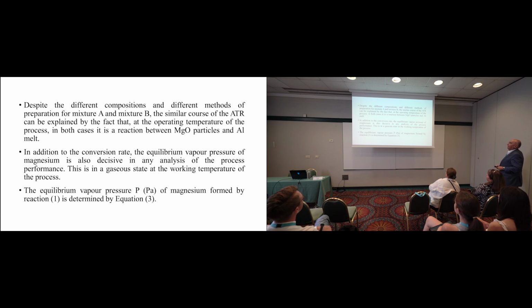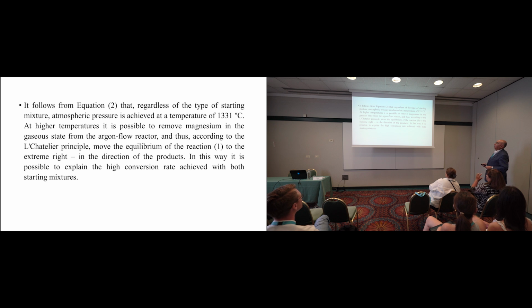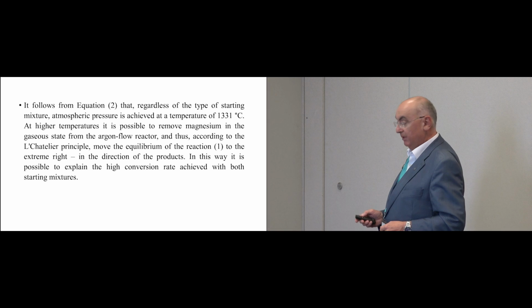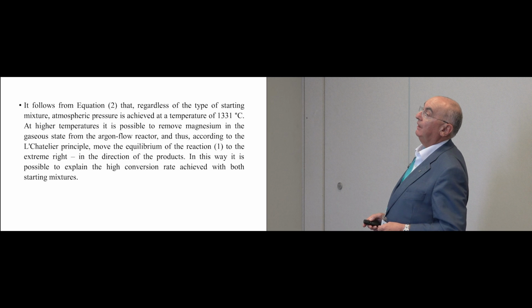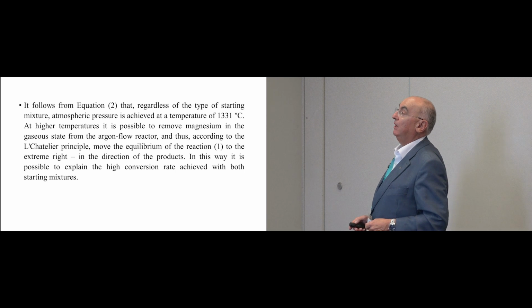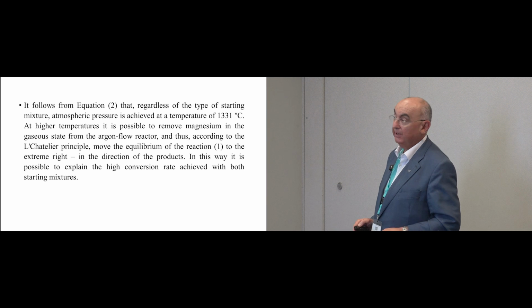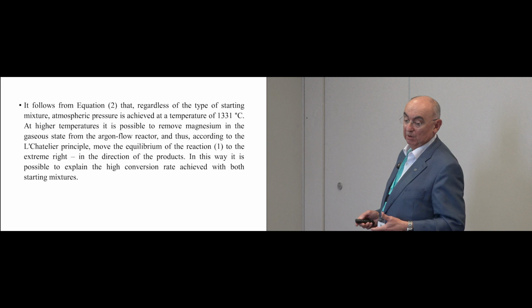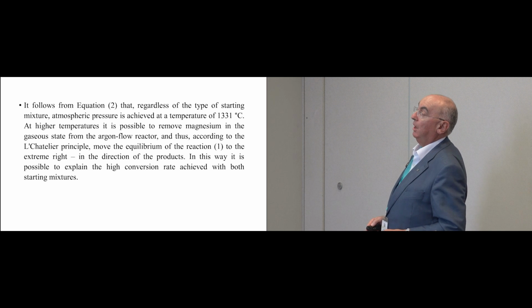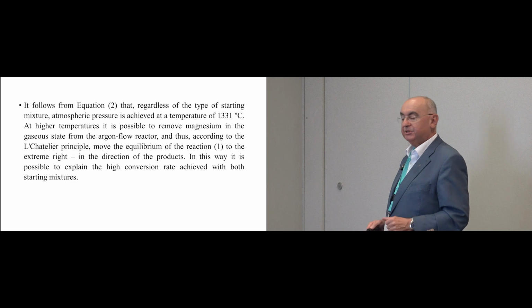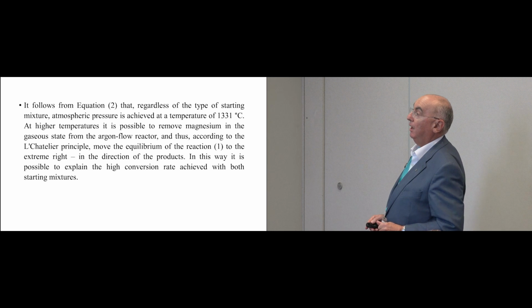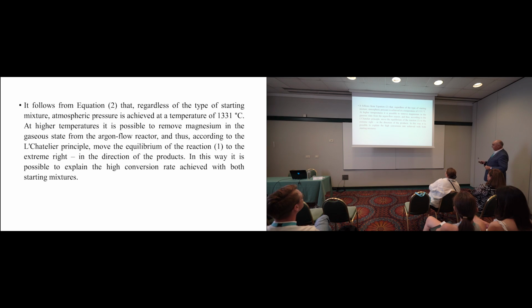So, of course, kinetics is one thing, but also the equilibrium vapor pressure, which can be calculated from the thermodynamic data, is also very important, and we found that under this condition it will be around 1 bar, which is perfect. Means that we can use argon flow atmosphere for removing gaseous magnesium from a chemical reactor.